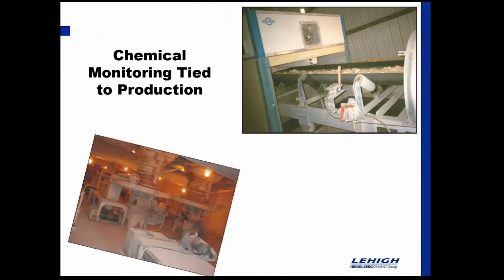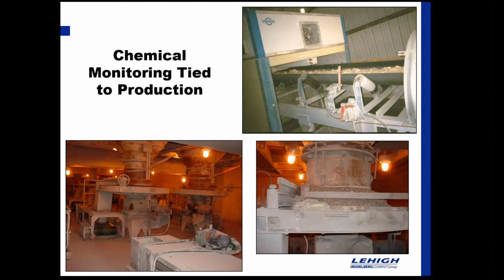And just all along the way, really, chemical monitoring is tied to production. If you've never been into a cement plant, it's an interesting place to take a walk through. And so there's different ways to do that. There could be cross-belt analyzers that give you a minute-by-minute readout of the material that's going on a belt. There could be, in these older situations here in those bottom pictures, tables that actually speed up or slow down depending on how much of the material is needed to get the particular element out of that for the production that you need.